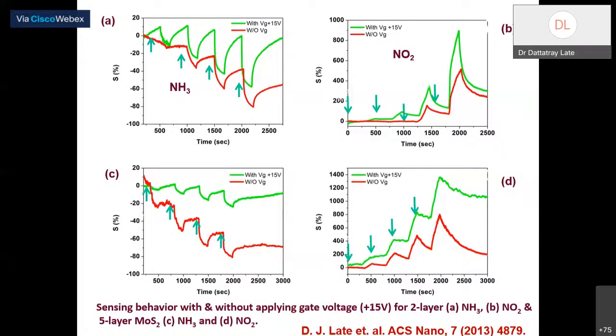You can see in one case the sensitivity is going down, in another case the sensitivity is going up, because these are n-type electron donating and electron accepting gas molecules, right? And basically, the moment these gas molecules sit on the MoS2 layers, the Fermi level of the MoS2 slightly shifts towards the conduction band, and because of that there is a change in resistance. That change in resistance, or sensitivity, can be seen in this particular sensor result.